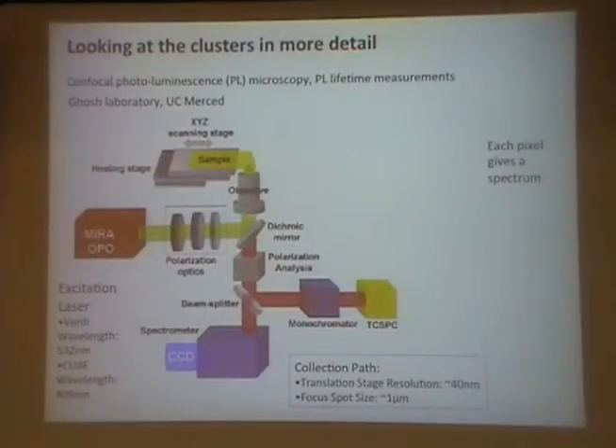So we've been working with a lab at UC Merced, the Ghosh lab, doing imaging and spectroscopy on particles dispersed in liquid crystal. What we have here is confocal photoluminescence microscopy. It's a setup where we look at the luminescence of quantum dots within a cell. You have a liquid crystal cell with the nanoparticles dispersed. Take an image of that cell, it's a confocal fluorescence microscopy image, and at each point in the image, we take the spectrum. So it's not just an intensity map, it's also a wavelength map of the sample.